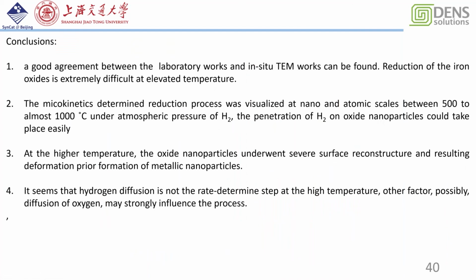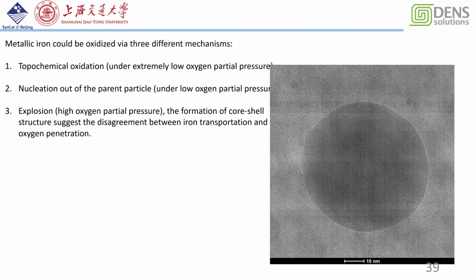Yeah, I didn't mention it very clearly here because it's quite fast. The topochemical oxidation happens below almost 0.02 Pascal. So with an extremely low oxygen partial pressure, you can see the topochemical oxidation process. But at ultra high oxygen pressure, about several millibar, you can see the explosion of the iron by the oxygen.